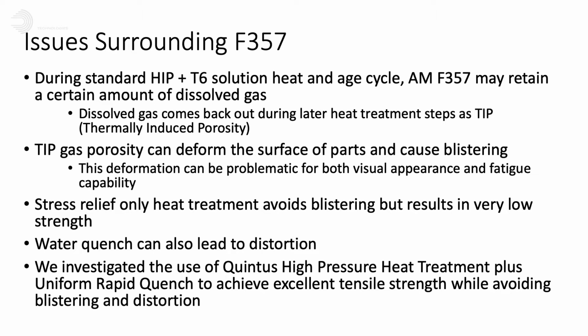The other issue is that the users out there have been typically avoiding the blistering issue by simply avoiding high temperature heat treatments, avoiding the solution heat treatment and age process altogether, and just using an as stress relief condition. In doing that, they're trading away a lot of the yield strength capability of the material. And so while you can avoid blistering by choosing to stick with a lower processing temperature, oftentimes that leaves you with worse mechanical properties. And so we're looking at ways to get everything that we want from the alloy: good mechanical properties, low distortion, and no blistering.